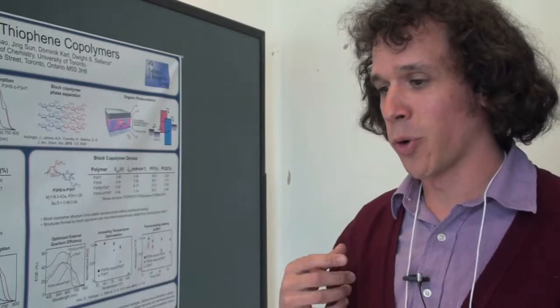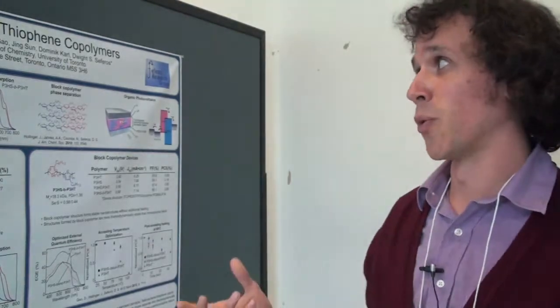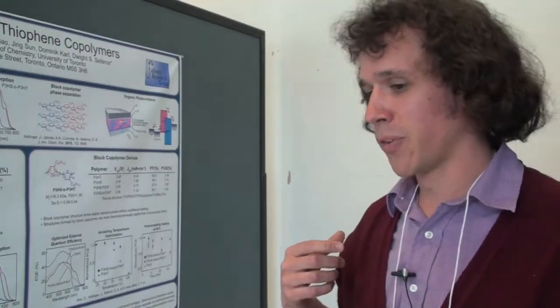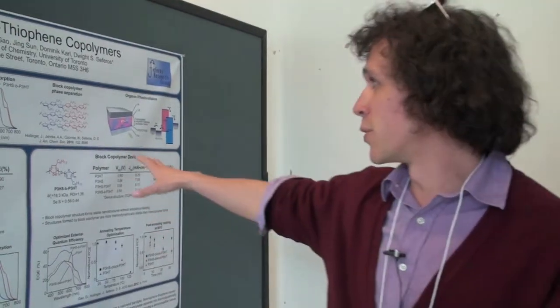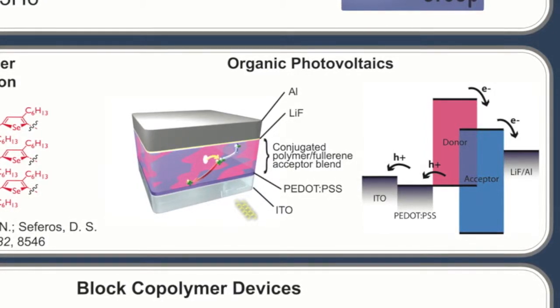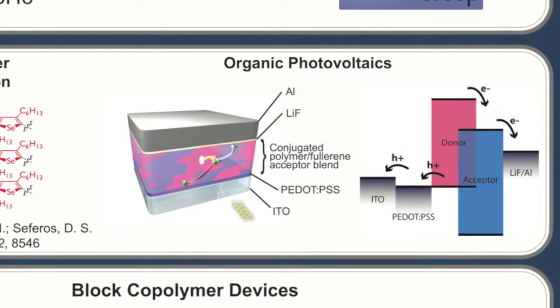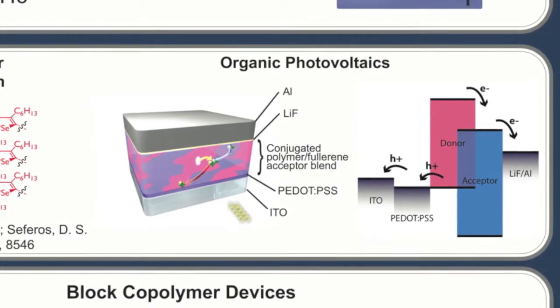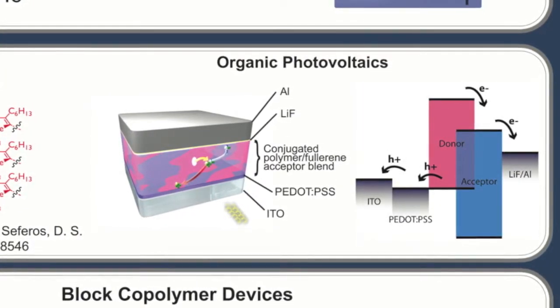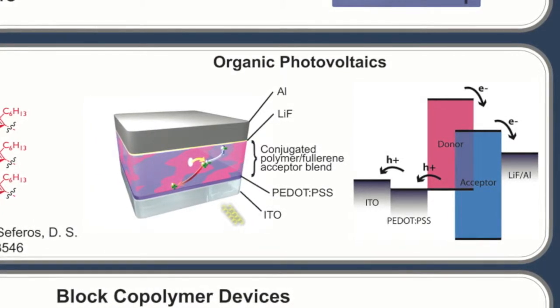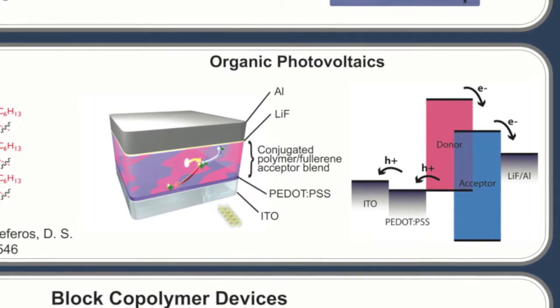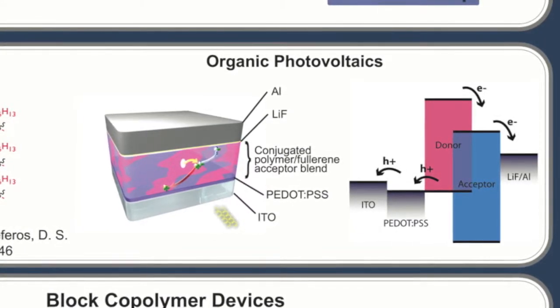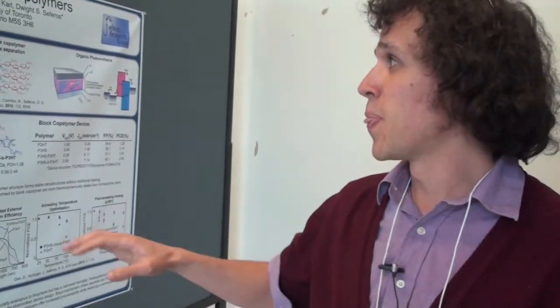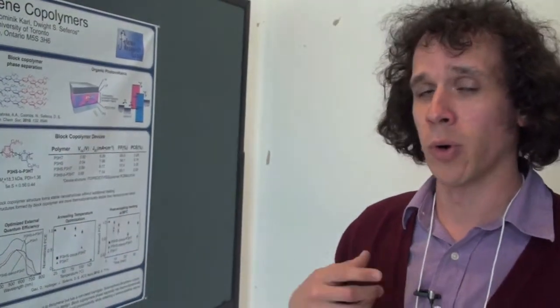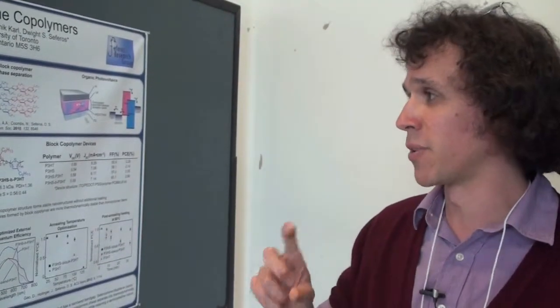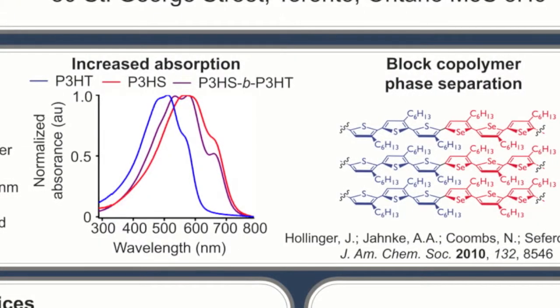First of all, it doesn't absorb as far into the red wavelengths as would be optimal. And since morphology is so important in a bulk heterojunction cell, which is the kind that we fabricate, we wanted to look at making a block copolymer with one block of polythiophene and one block of polyselenophene, which is the selenium substituted analog of polythiophene. Now, in a couple of initial studies that we did, we found that although these heterocycles are structurally analogous, the polyselenophene was known previously to absorb more into the red wavelengths because the band gap is narrowed. And you can see that just with the simple thin film UV trace.